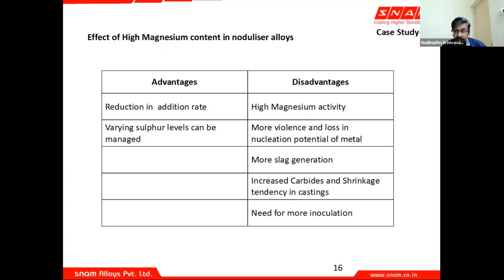and this in turn is going to reduce the nucleation potential, because during the turbulence, you're going to take away a lot of your inoculating other elements that are present, and they all get into the slag, and you lose the nucleation potential. Magnesium is a carbide promoter. And when you have carbides, you do not have free graphite for overcoming the contraction of austenite, and therefore you will have a shrinkage tendency, and you need more inoculation because a lot of the inoculating element nuclei that are present in the molten metal have been taken away in the slag.